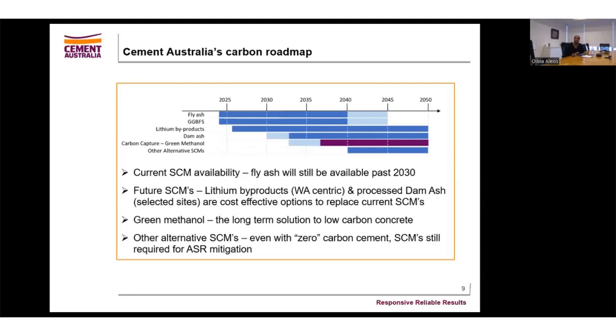If we look at this carbon roadmap, we believe that we'll have fly ash and slag up into 2040. And that's going off, say, the closure dates of power stations. We might have lithium byproducts that will kick in after 2025, and that will be more Western Australia centric. But as that comes online, that should assist with elongating the lifespan of slag. And then we'll probably have some readily available binders such as dam ash that could come online just before 2035. And then most importantly for Cement Australia, we have green methanol carbon capture, which I will talk about in more detail later on in this presentation.